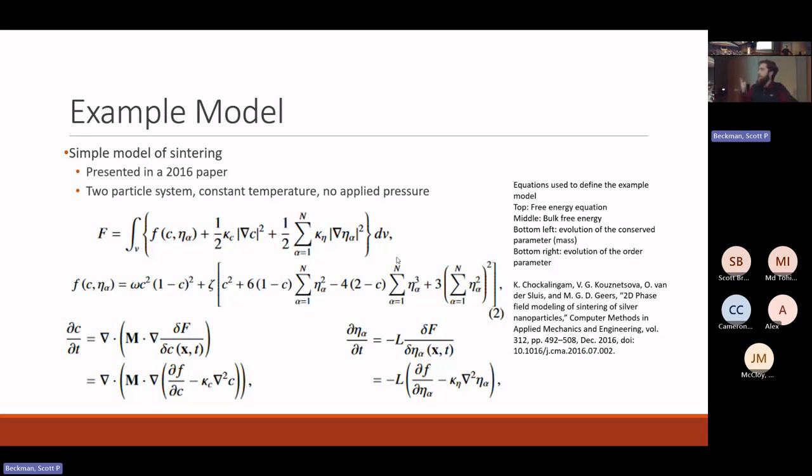However, as I mentioned previously, this first free energy equation is not actually directly solved. Instead, two equations that define the phase field model and determine the evolution of the system are the bottom two. The equation on the left describes the mass continuum equation and defines how material diffuses through the model.